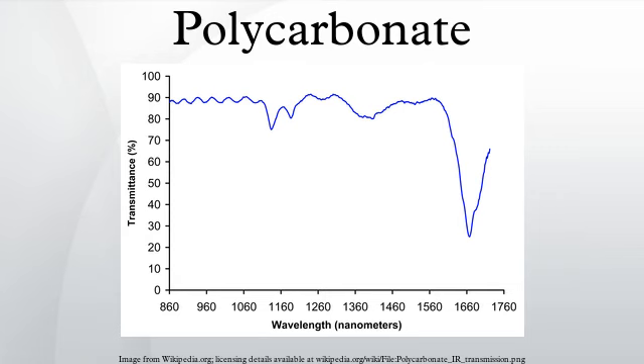Although it has high impact resistance, it has low scratch resistance, and so a hard coating is applied to polycarbonate eyewear lenses and polycarbonate exterior automotive components. The characteristics of polycarbonate are quite like those of polymethyl methacrylate, but polycarbonate is stronger and usable over a greater temperature range. Polycarbonate is highly transparent to visible light, with better light transmission than many kinds of glass.